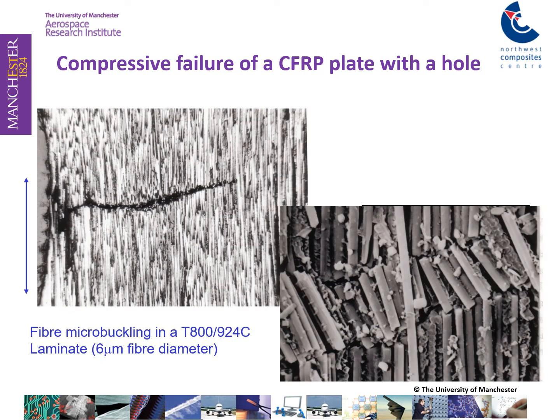Here is this crack that resembles a fatigue crack in metals under tension, but here it is static uniaxial compression. At the higher magnification in the scanning electron microscope, we can see the buckled fibers, and this is a critical damage mode, very brittle in nature. When it reaches a critical length of 2 to 3 millimeters, it depends very much on your material properties and the laminate stacking sequence, it becomes unstable, leading to catastrophic fracture.